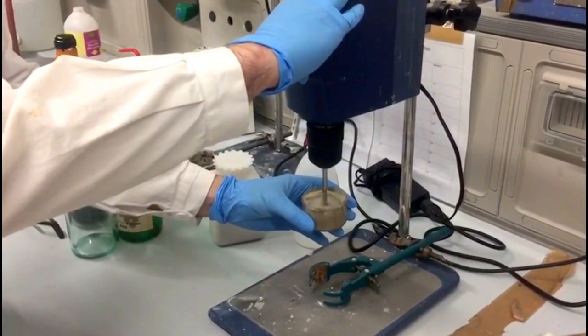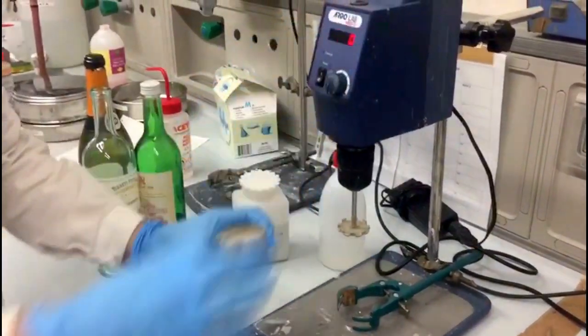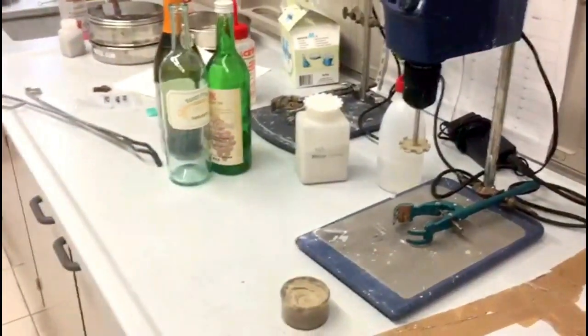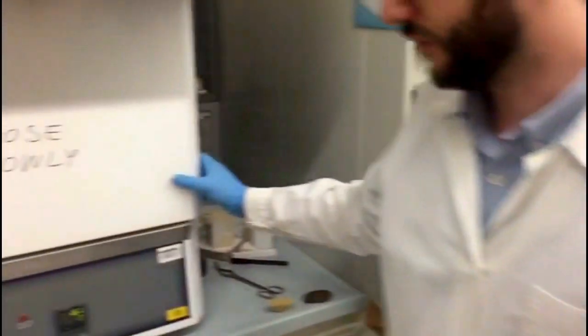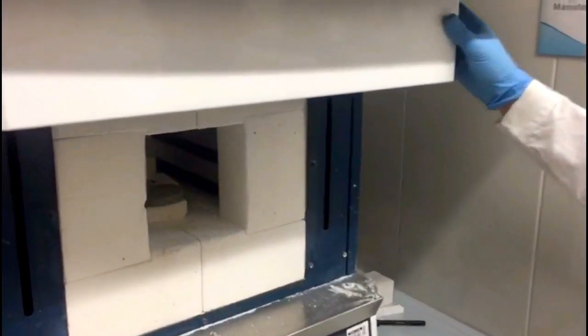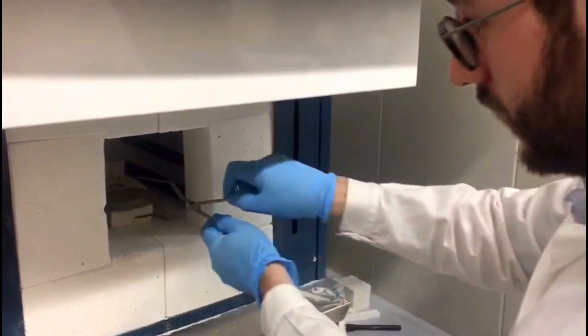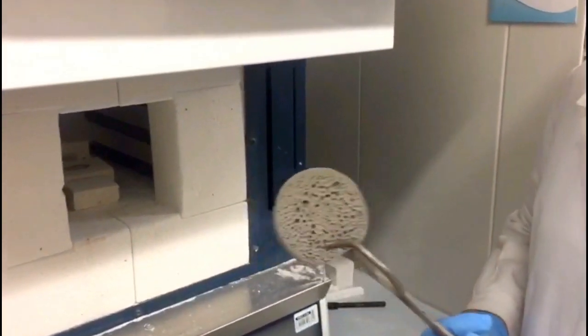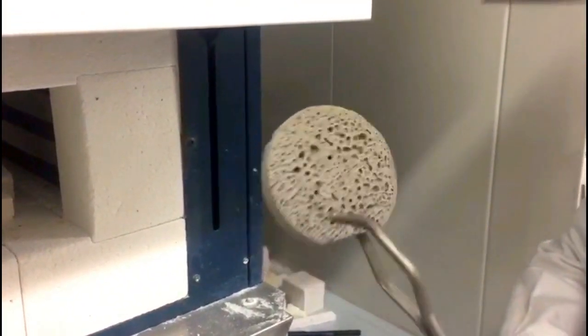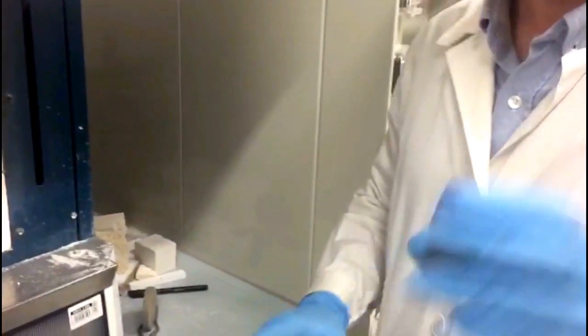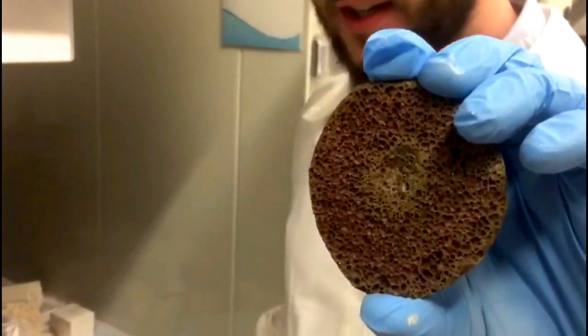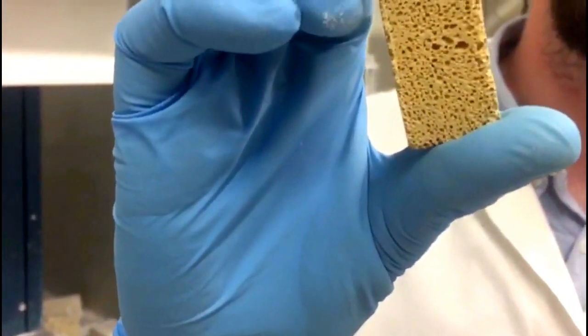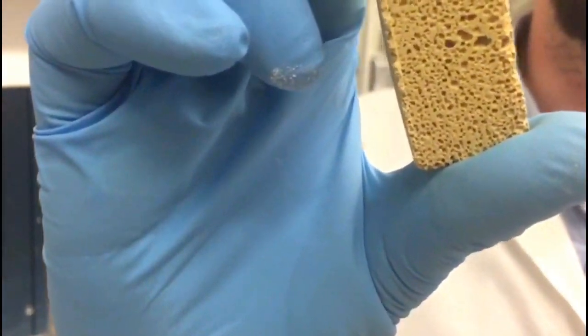When the foam is done, we just dry it and put it in the furnace. After this treatment, we have an insulation material that could be used for building. With the same technique, we have also developed some material with copper slag or with municipal solid waste bottom ashes.